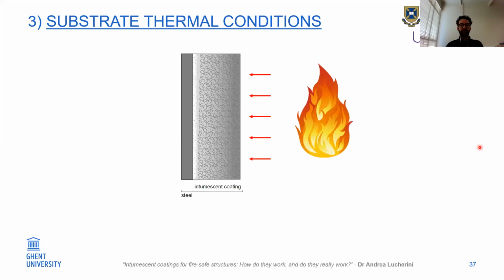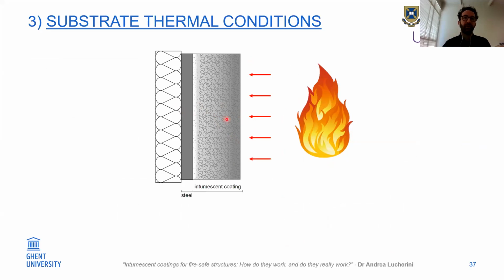Finally, the last experimental campaign I would like to show you focuses on the substrate thermal conditions. What I can show you here is that I have my fire. In my case, I have a radiant panel that applies a certain heat flux on the surface of the coating, which swells, and I have my steel plate at the back. What I've been doing so far is isolating the steel plate. So all the heat that penetrates through the coating collects inside the plate, and no heat, in theory, or only a small part, can leave the plate from the back because I used an insulating material.